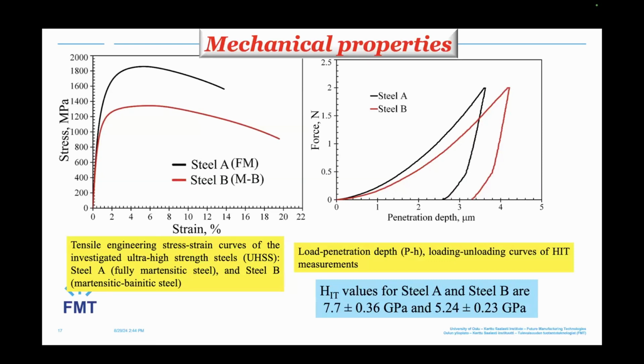Using microindentation hardness, we can see the loading and unloading curve just before fatigue, to know the microindentation hardness, the HIT, using a Berkovich indenter. For steel A, because of the hard matrix, we found an indentation hardness of about 7.7 gigapascal, but for steel B, including 50% bainite, the hardness decreased to 5.24. So these are the mechanical properties from tensile tests and microindentation hardness for both steels.